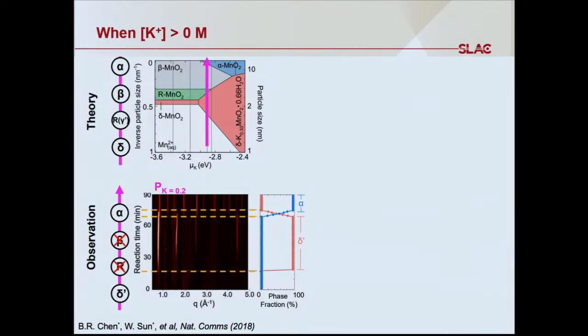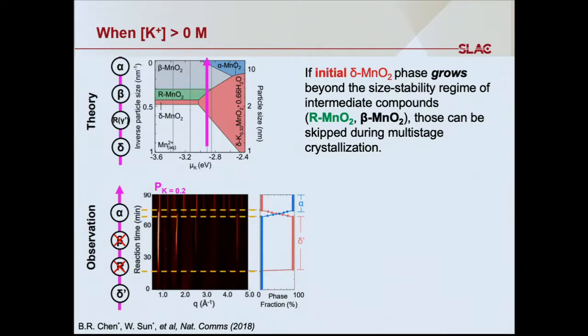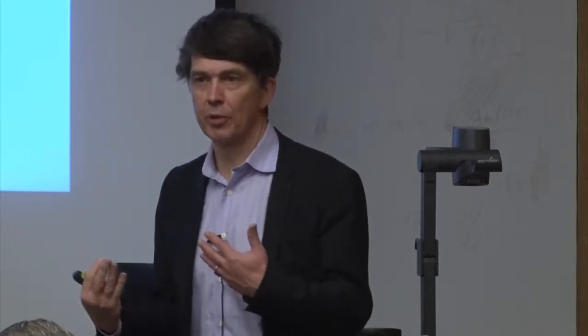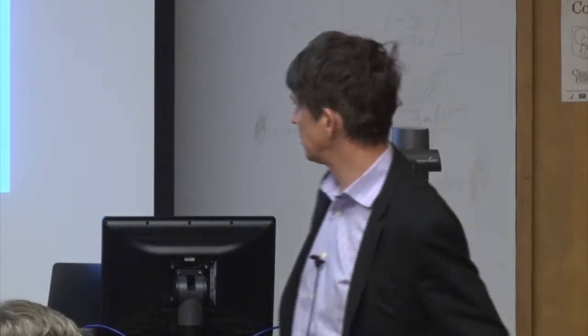And what's actually happening here is that the delta phase forms, and then it grows so fast before the other ones can nucleate, and it goes straight to the alpha. So in some sense, it's not giving the other ones a chance to exert their preference because the size has already grown so much that these are not stabilized by size anymore. And so this is clearly something we cannot predict yet, right? When you have competitive phenomena, it could either nucleate, say, beta out of solution, or it could just rapidly grow in size. We cannot predict that competition because that would require that we actually predict all the rate constants for all of this. So we sort of get the sequence, but we can't predict which phases it skipped.